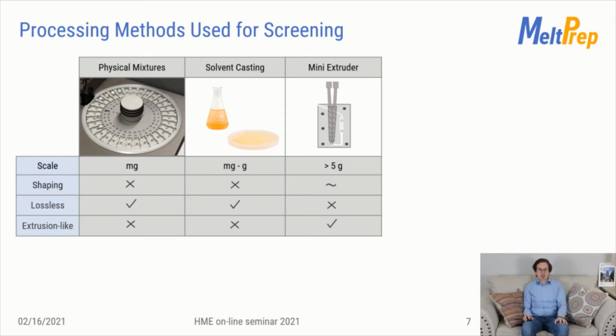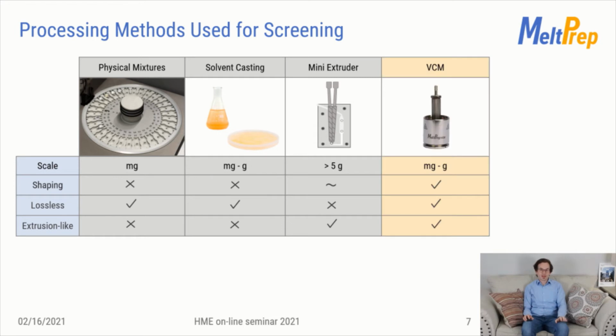You're most likely familiar with the typical screening methods that have been used so far, with all their benefits and also with their challenges. We need an extrusion-like method in the early stages to allow easy scale-up to manufacturing down the road. This was only possible by the use of lossy miniaturized extrusion equipment in the past. Many times this route was not pursued as simply not enough material was available to do that. My invention now extends the playgrounds for the scientists in the field.